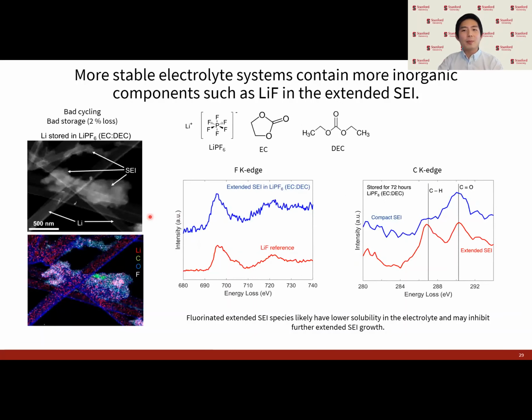In comparison, this LiPF6 system, which only has the salt anion, the perchlorate, swapped out for a PF6 anion, shows much less storage loss, only about 2% after 72 hours, along with an extended SEI that, based on the fluorine K-edge chemistry, appears to be rich in lithium fluoride. In addition to this inorganic lithium fluoride component, there still is some organic deposition products coming from the solvent, and that's indicated by the carbonate peak along with this carbon hydrogen peak as well.